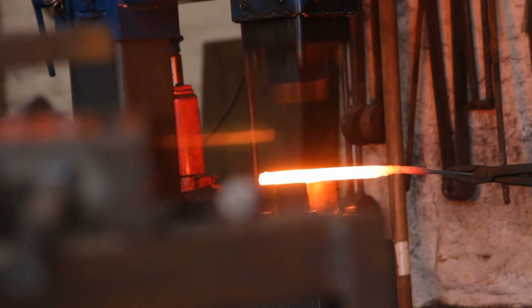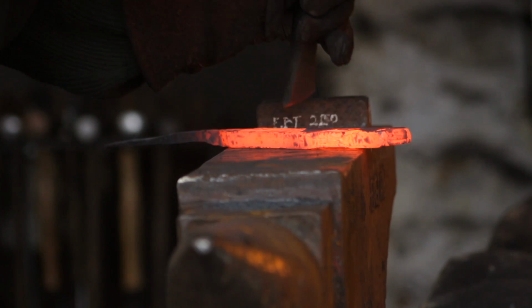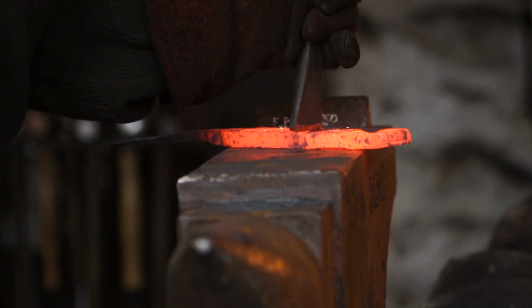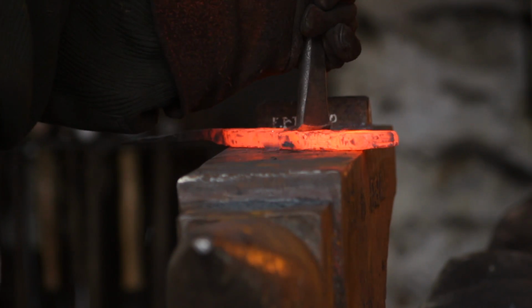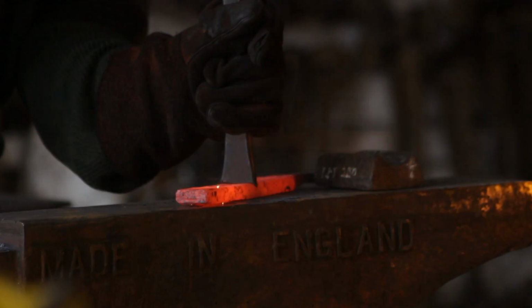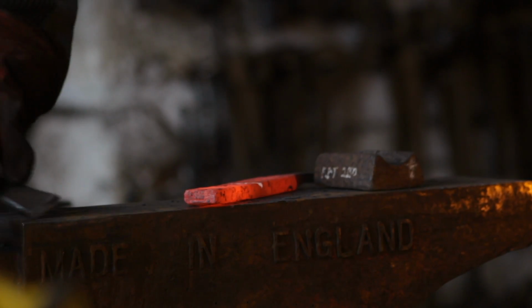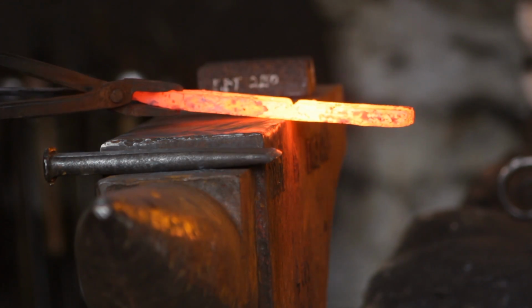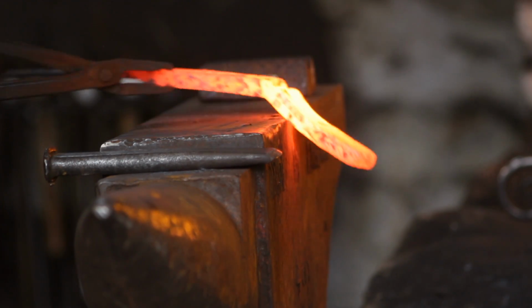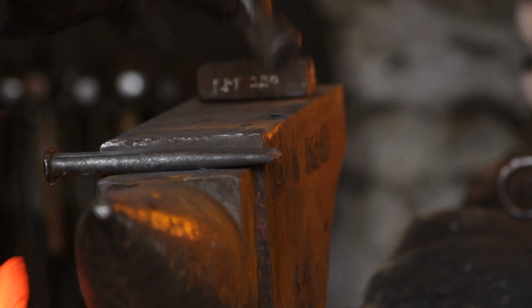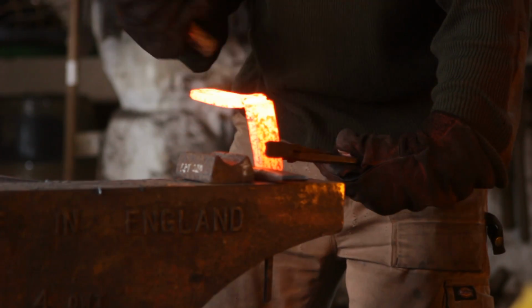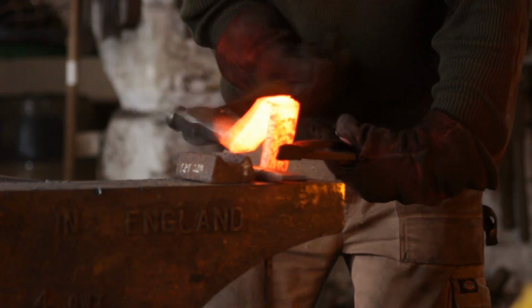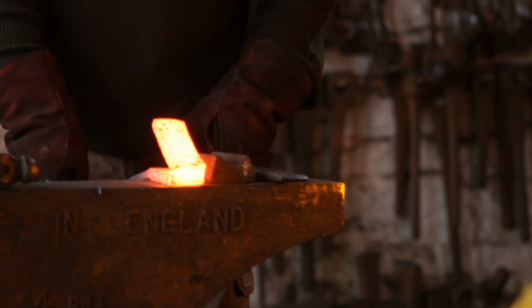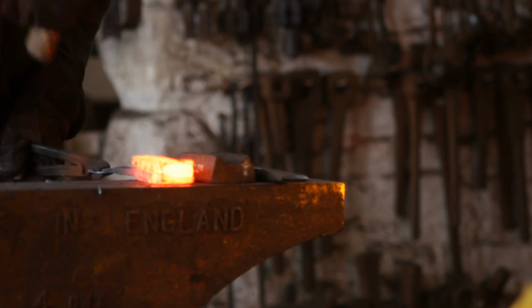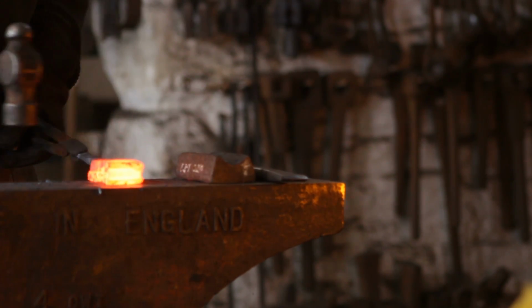And then, same as making a pattern welded billet, I will cut halfway through the material with a chisel. And then I will fold it over. And folding of this was a little bit awkward, mainly because I've got that tiny little stub to hold on to. Now you can use your Pritchell hole for this, as I do quite regularly. Doesn't really matter if you damage the bottom bit because that's going to be cut off anyway. So just fold that over and get it to a welding heat and weld it up.